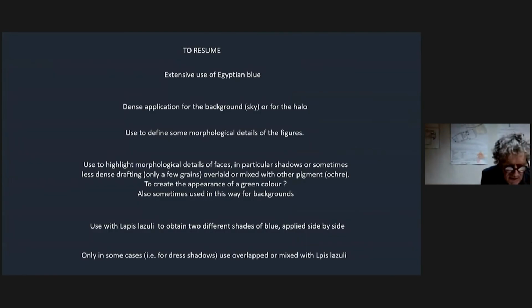To resume, in Müstair there is extensive use of Egyptian blue: a dense application for the background for the sky, a use to define some morphological details of the figures, a use to highlight morphological details of faces, in particular shadows, sometimes with a less dense drafting, overlaid or mixed with other pigment to create the appearance of a green color. Also sometimes used in this way for the background. A use with lapis lazuli to obtain two different shades of blue applied side by side. Only in some cases, for dress shadows, it is used overlapped or mixed with lapis lazuli.